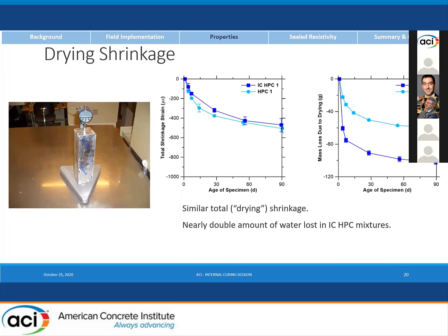In terms of the drying shrinkage, we've measured it here. It's perhaps not the most obvious or best test for understanding the true difference for what internal curing is doing. But what we see in the difference primarily is the mass loss. So to get to an equivalent shrinkage, you have to lose almost twice as much moisture from the specimens. And that's the primary takeaway. And so there's a lot of enhanced robustness to drying shrinkage built in here.